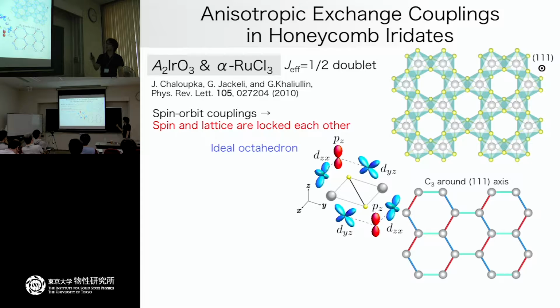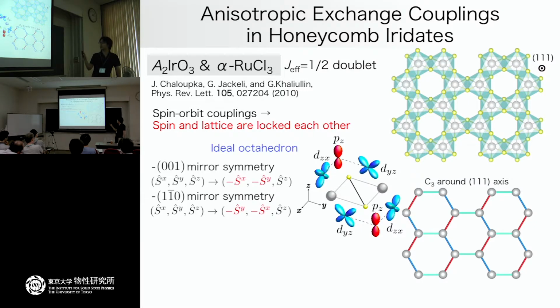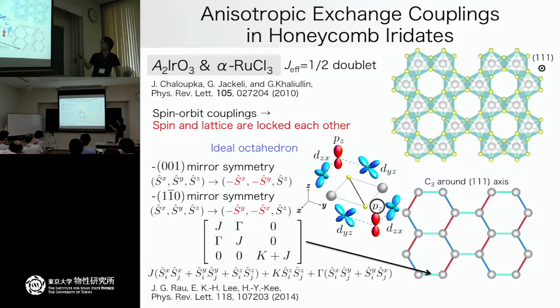From the symmetry of the oxides or halides, ideally this iridium or ruthenium ion is surrounded by oxygen atoms, and the oxygen atoms form an octahedron. If we have an ideal octahedron, then the iridium ions are connected by 90-degree bonding from the d orbital to the p orbital in the oxygen and the d orbitals. If you utilize this symmetry, for example here along this bond, we have a 001 mirror symmetry and a 1-10 mirror symmetry. Then the symmetry-allowed interaction is given by this. In this matrix representation for the exchange coupling, three independent coupling constants can appear.